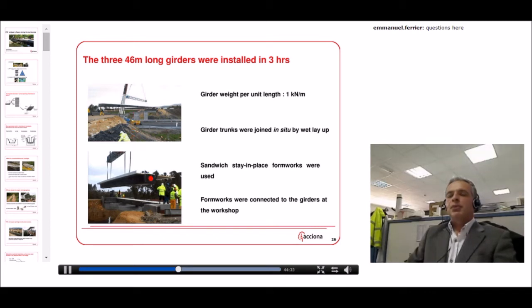To speed up the installation process, we use stay-in-place formwork, as you can see here, that was already connected to the girder before installing the girder. So once you put the girders on the supports, you can immediately put the reinforcement in place. You can start pouring concrete immediately. Due to all this innovation, the 46 meter long girders were installed in only 3 hours. This was very successful in shortening the installation time of the bridge.